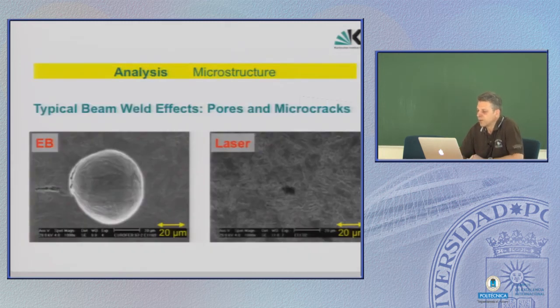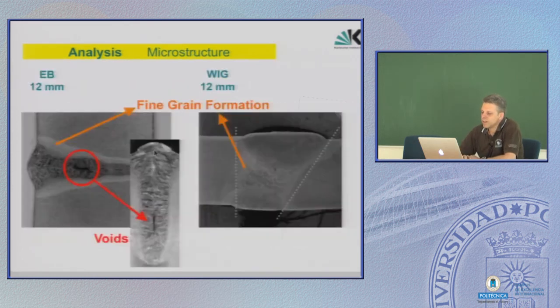Other drawbacks of beam welding are that they easily produce bubbles inside the material, depending on the gas which is still in any steel or material. Also small voids, like here in the laser beam weld. Another drawback is if the volume of liquefied material is too large and the quenching or solidification rate is too high, then you are typically left with cracks or holes along the solidification line inside the weld.